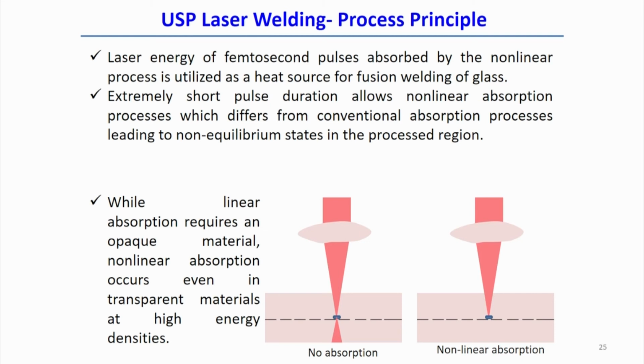Now we will try to discuss this ultrashort pulse laser welding process from the perspective of application in non-metallic material. Laser energy of femtosecond pulses is absorbed by a nonlinear process and utilized as a heat source for welding of the glass. Normally we find huge application of the ultrashort pulse laser for the joining of glass. Extremely short pulse duration allows nonlinear absorption of the energy by the material, which differs from the conventional absorption process, leading to non-equilibrium states in the process region.